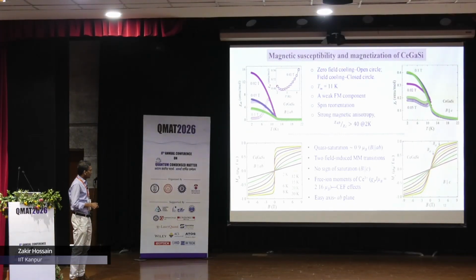But you see the M versus H. So for B parallel AB, it rapidly increases and then saturates. B parallel C is slower and then kind of quasi-saturation. So all these give a hint that it's an antiferromagnet, but not a compensated pure antiferromagnet. And which can also be realized from the M versus H. So at low field, it's a linear increase, but then it saturates.